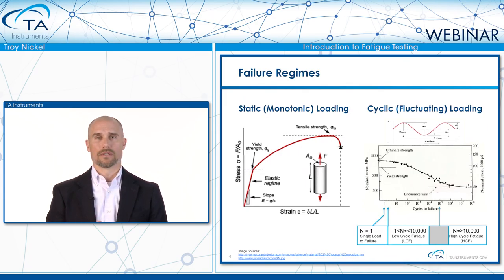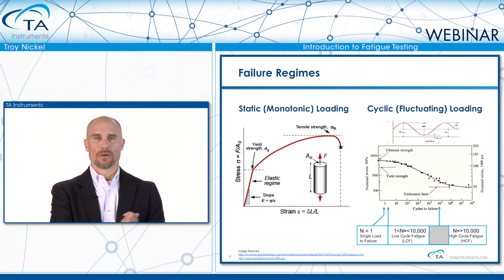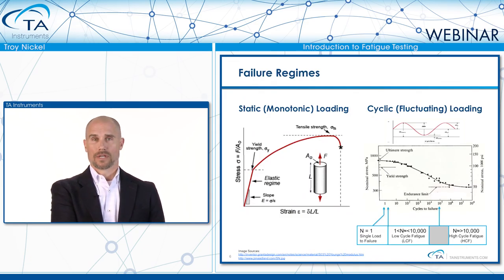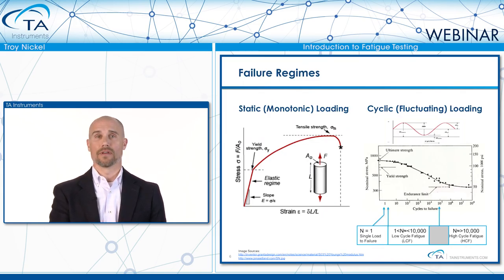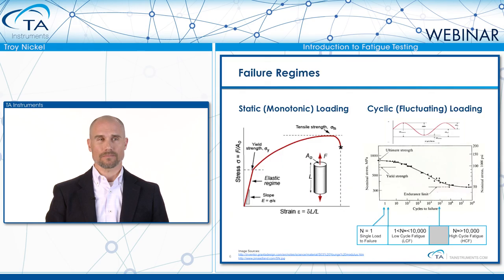The different regimes: we have a single load, and then fatigue splits into low cycle fatigue and high cycle fatigue. The transition is generally around 10,000 to 100,000 cycles. In low cycle fatigue the material is plastically deforming repeatedly and fails sooner. In high cycle fatigue it's generally in the elastic region and lasts longer, but will still eventually fail.